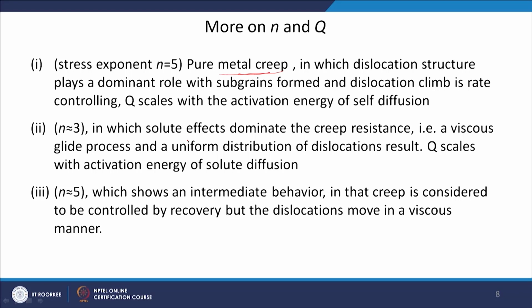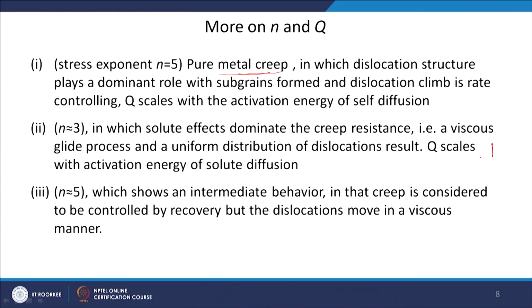If n is equal to 3, in which case the solute effect dominates the creep resistance. So you know that when we are developing alloys, there will be some solute atom inside the material. And what this solute atom do is they go and collect in the core of the dislocation. I do not know whether you know that. Let us say a simple example of edge dislocation, which I can draw like this, this is my extra half plane. Because you have an extra half plane here, you have compressive stresses here, and tensile stresses below the slip plane.